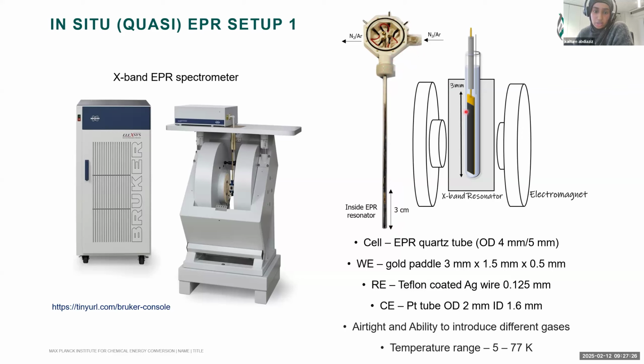For the working electrode, I use a gold wire, which I flatten to increase the surface area. My reference is a silver wire, which is a pseudo reference because I am not able to use a real reference due to space constraints, and then a platinum tube as my counter. In this system, I typically work in the range of 5 K to liquid nitrogen temperatures.